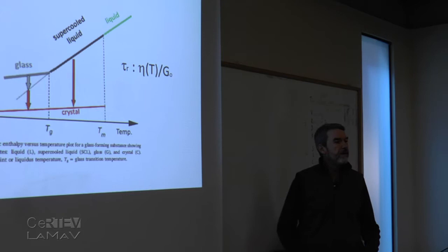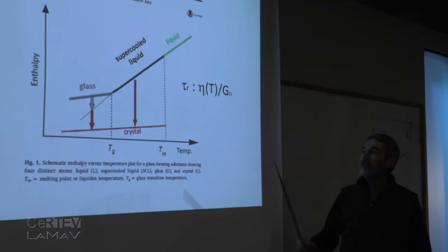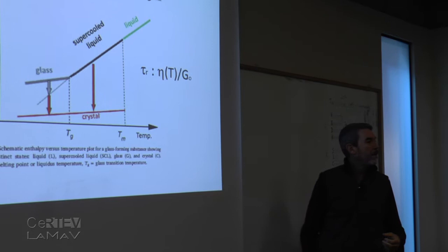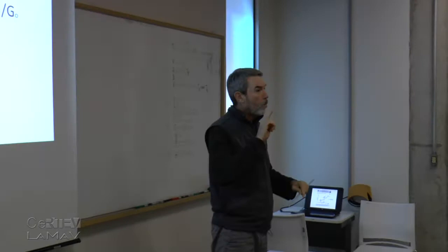It's a point where the experimental time or the measurement time is shorter than the relaxation time. So the liquid can no longer relax. It freezes in without crystallizing.